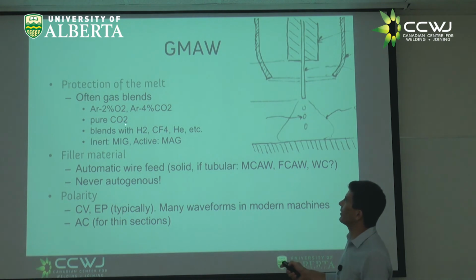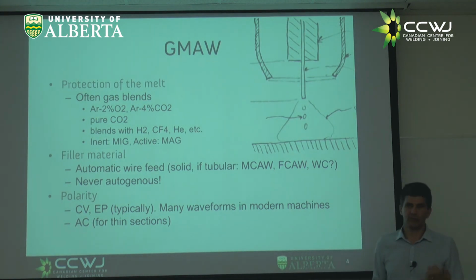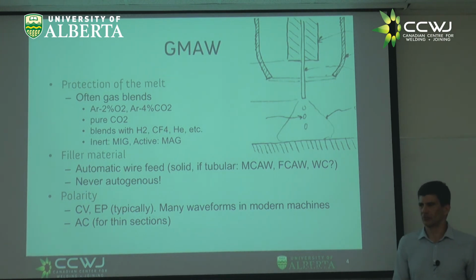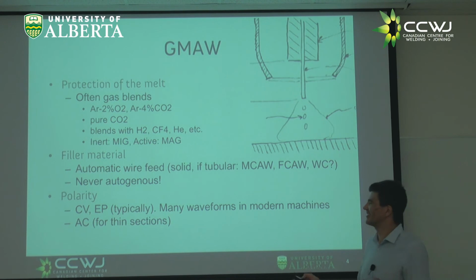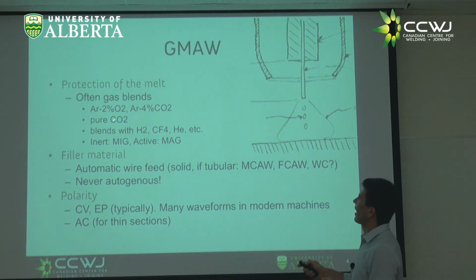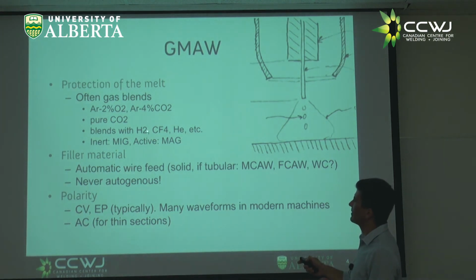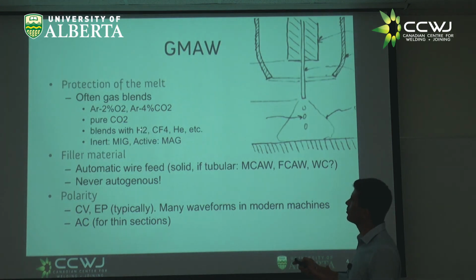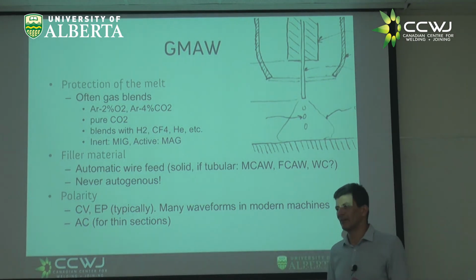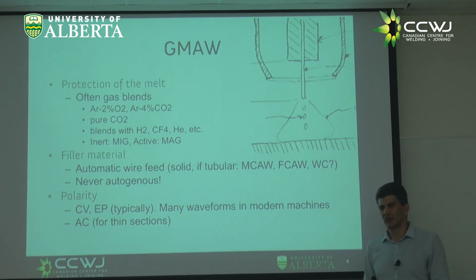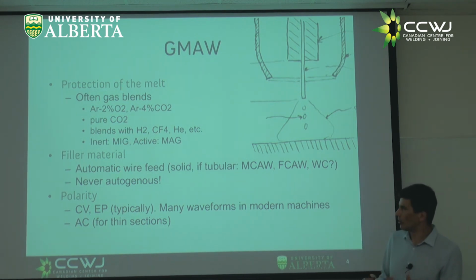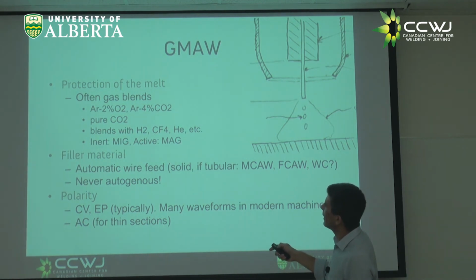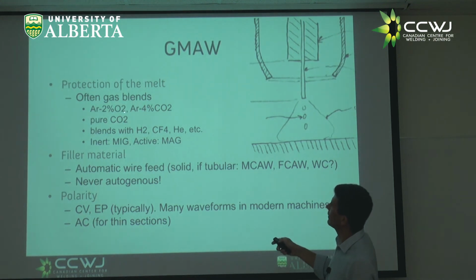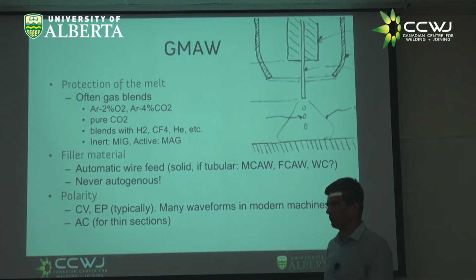And now I can play games. For example, I can use pure CO2. Guess what? CO2 is a lot cheaper than argon. Actually, we pay to get rid of CO2, and then you go and buy it. Who knew? It's interesting. So you can have blends with different gases. Gases like hydrogen, or CF4, a crazy gas in which you put small amounts, and the fluorine will react with the hydrogen and suck up the hydrogen to give you low hydrogen welds. You can use helium. And also you can use mixtures of argon and oxygen, or argon and CO2.